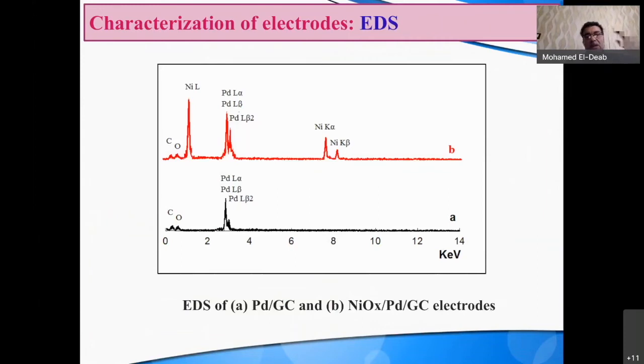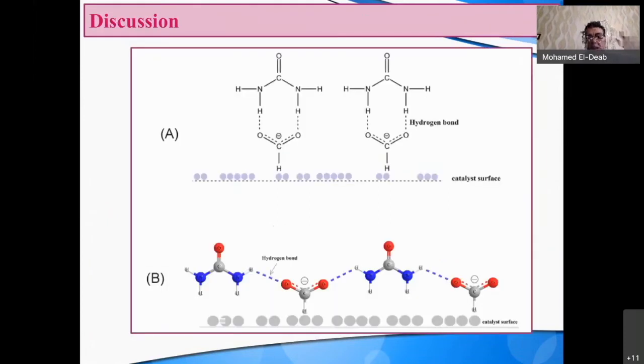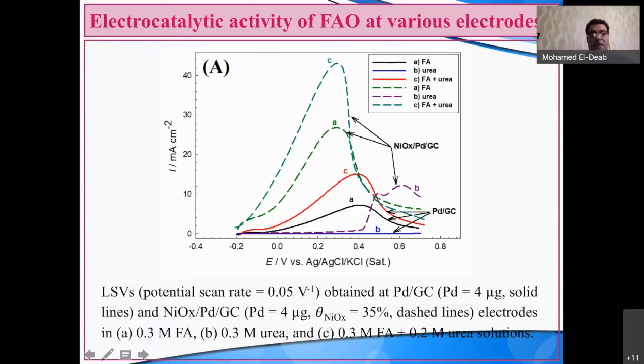Here we can see that for this CV, we have here LSV for formic acid oxidation. For case A, just formic acid, solid line, this one, palladium nanoparticles deposited on glassy carbon, and in presence of urea, this one jumped up to this green one. So the presence of urea here enhances the oxidation of formic acid more than 3 times. This is not due to the oxidation of urea, because urea oxidation is not possible in this potential domain. As you can see, this blue line corresponds to urea oxidation.